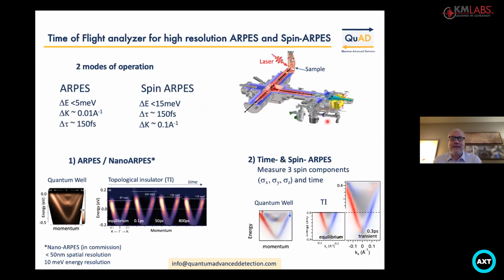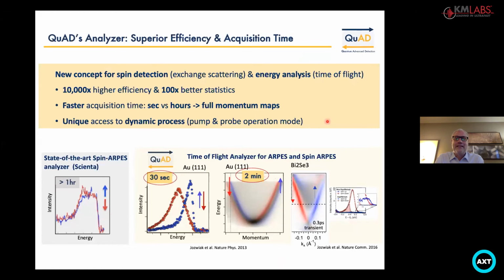But one thing that we're very excited about implementing is that there are new ideas for implementation of angle resolved photoemission spectroscopy that will allow for spin resolution, so that you could not only get the energy and momentum picture of the band structure, but look at spin for magnetic materials and spintronic materials. And this is a startup company that we're starting a collaboration with to demonstrate this technology. It's a very efficient instrument because it uses the time structure of the laser specifically to allow for very high data acquisition rates. So it's a different technology than is used at the synchrotrons, and it's ideally suited for use with these megahertz rep rate laser sources.